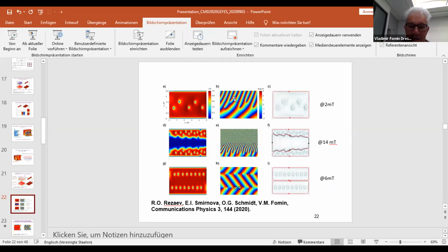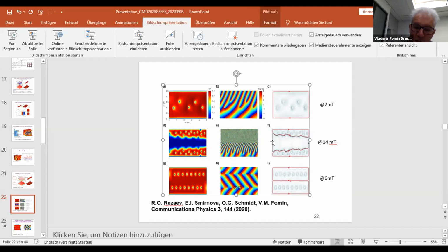representing the order parameter, its phase and currents, we will see that the planar structure reveals a set of vortices, and if you increase the magnetic field, a phase slip enters. But in this case, we have three loops of screening currents, one of them around the phase slip. And in the case of a tube, we have two sets of vortices inside the loops.